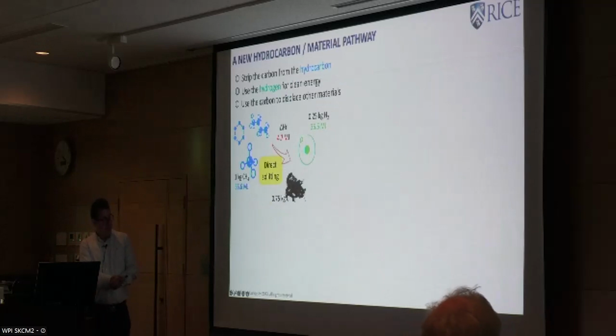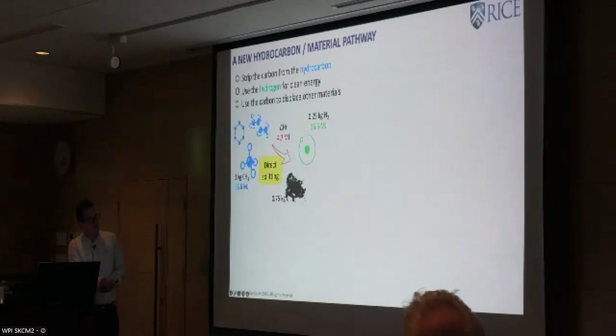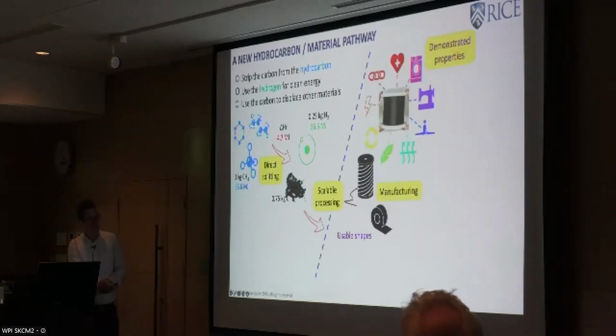We do it with methane, which is harder to split. The energy works out that at least you need 4.7 megajoules per kilo of methane, but you get at most 35.5 megajoules per kilo of methane in terms of hydrogen. However, if you make the right type of carbon, you could then turn this into macroscopic materials.